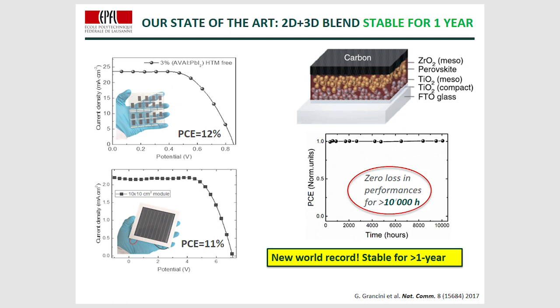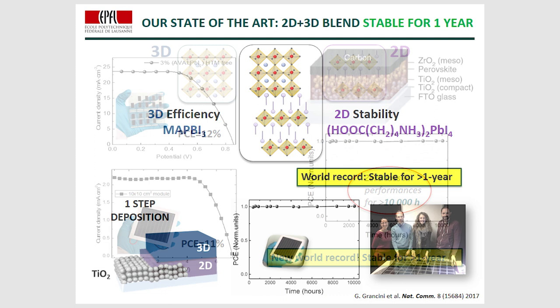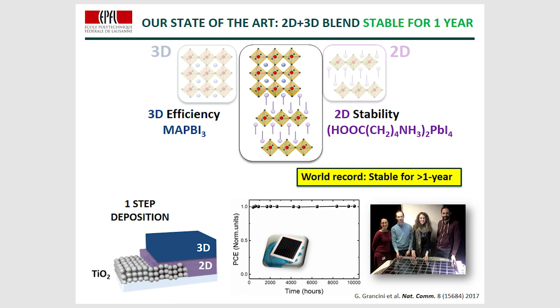Even if the efficiency is not so high — 12% in the case of the devices and 11% for the 10×10 module — it was possible to create in only one deposition step this gradient between 2D and 3D, yielding really stable devices with a lifetime of more than one year.